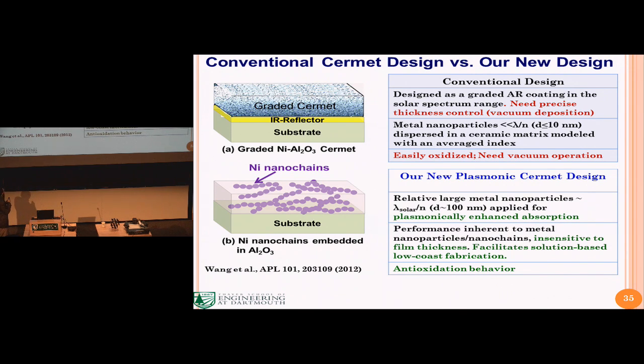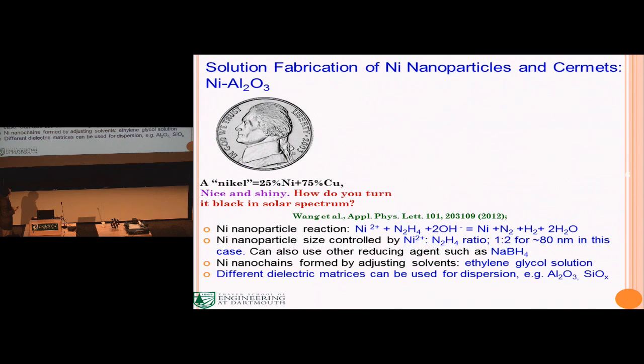So our approach is to introduce much bigger metal nanostructures and utilize the intrinsic optical response, that is, the free electron oscillation frequency inside the material, to efficiently absorb light. And because the optical properties are inherent to the nanostructures of metal, it doesn't depend too much on the thickness. So we can use very cheap chemical solution methods to fabricate these coatings. And we can also achieve anti-oxidation behavior, as I will show you in the next few slides.